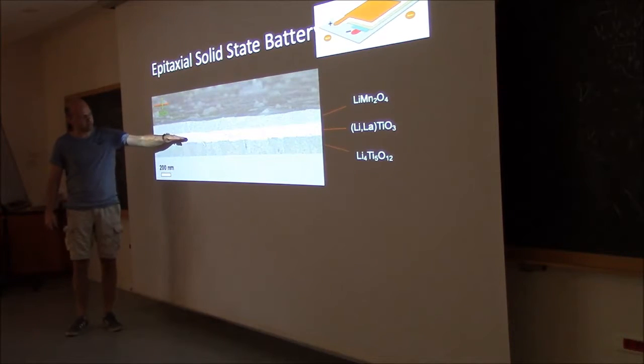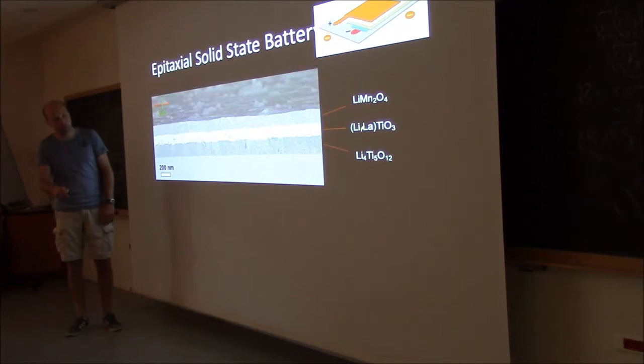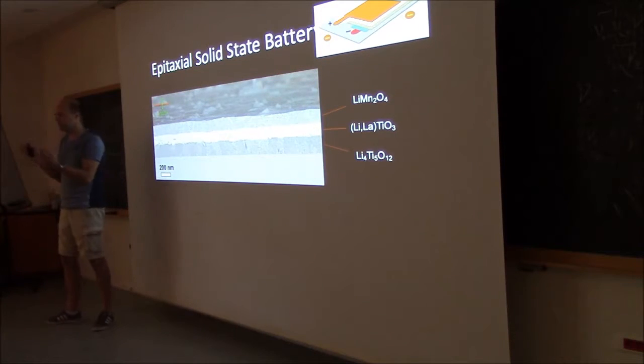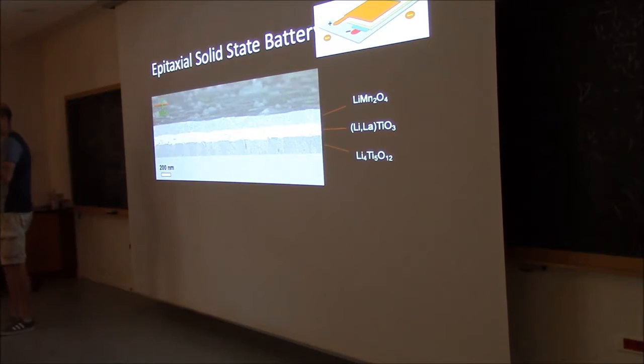The point is that the ionic conductivity of this layer doesn't move the ions as well as it should be, because there is a very subtle balance between, on the A side, the amount of lithium there, the amount of lanthanum there, and vacancies, because they have to be there as well.